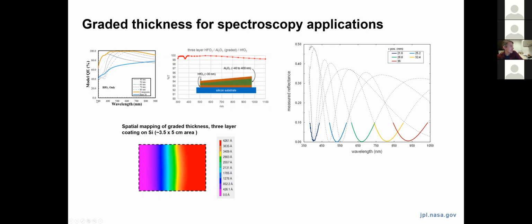And so we've made some of these test coatings initially for a test coating operating in the visible and the near infrared that was intended to maximize the overall transmission from 300 to 1,000 nanometers. And so again, for any single thickness uniform layer, you might get a profile like the dashed lines shown on the left over here, which is relatively high quantum efficiency, but maybe at most you can get an average QE of 80% across this band. If you could tune its thickness gradually as a function of the dispersion, you could do a lot better than that with just hafnium oxide. And with a 3-layer stack, as I'm showing in the middle here, you can theoretically create a device that has greater than 99% quantum efficiency across this whole range.